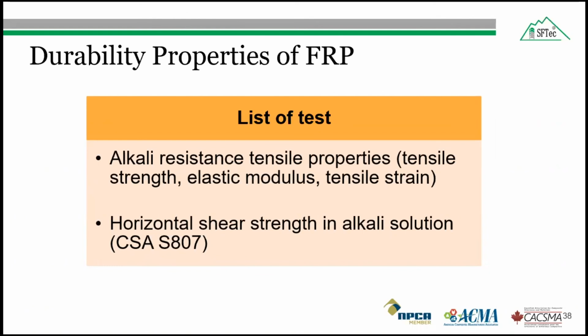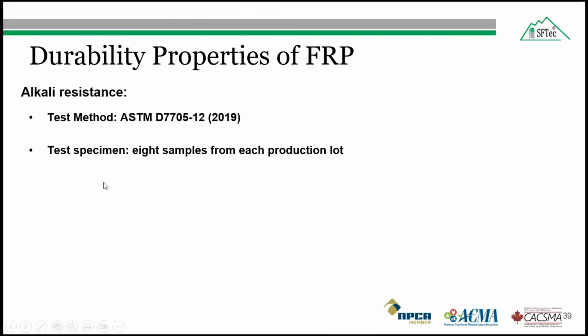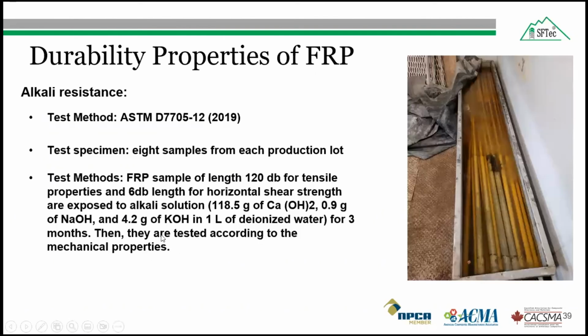And here 2 tests are required. One is required by both codes, which is the tensile properties, and the other is the horizontal shear strength in alkali solution, which is only required by the CSA S807. For the alkali resistance test, we follow ASTM D7705, and a total of 8 samples from each production lot are tested. Total 3 production lots are tested. Therefore, the total number of samples is 24. So the alkali resistance consists of two tests: tensile properties and horizontal shear strength.